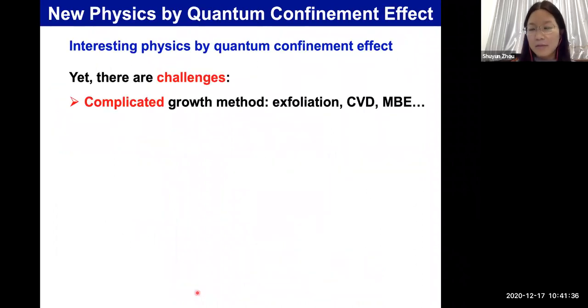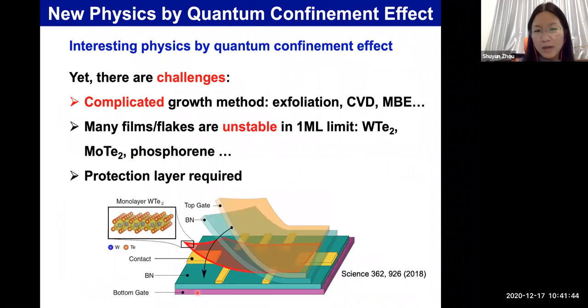First of all, this monolayer tungsten ditelluride is actually quite difficult to exfoliate or grow. And also, the sample is very unstable in the monolayer limit. And actually, for many metallic samples, this is a common issue, namely the sample stability. So therefore, a protection layer is typically required to protect the actual monolayer sample.